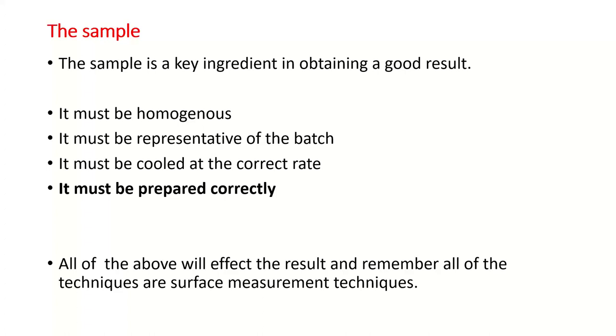And then cooling rates. A sample needs to be quenched fairly quickly to make sure that all the elements remain within that sample. They don't come out of solution and go into grain boundaries. A typical example of that is carbon in high carbon cast irons, SG irons, these sort of things, that as a sample cools slowly, the carbon goes off and goes into the grain boundary. And that will give you problems for measurements because it's sitting there as little globules of carbon that you actually measure. So it fires little explosions off during the time. So you don't get a homogeneous result. You get a variance in there.